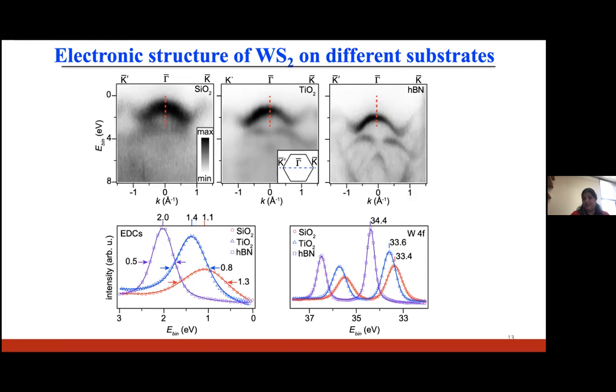And it is not surprising, because we know that on silicon oxide substrate, there are a lot of charge impurities, and also it's not atomically flat, right? So because of that, we get a lot of broadening of these bands. And similarly on titanium oxide substrate, what can happen is that because of the photon beam, there can be a lot of oxygen vacancies, which can again cause the broadening of the bands.